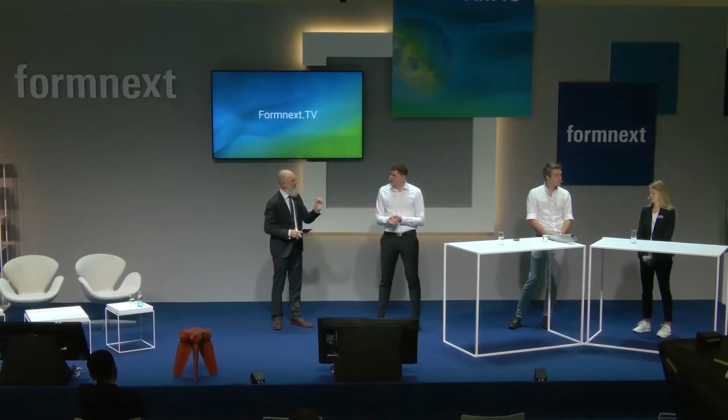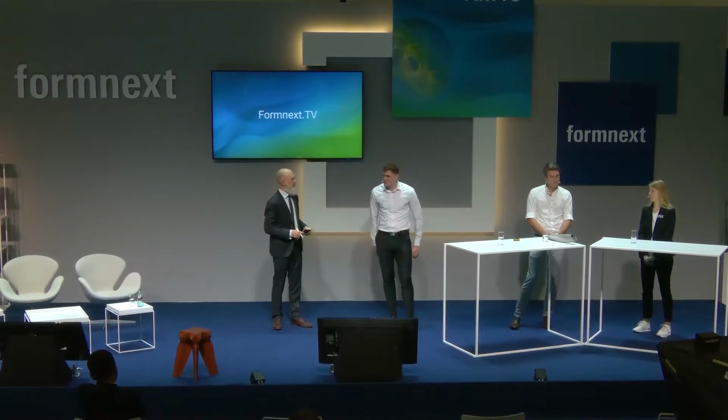But may I interrupt you? What is the droplet size? What is the finest surface you can achieve? The minimum droplet that's possible right now is 270 microns. So you can always see this shape at the surface of those parts. When you use a very small droplet, there's a surface quality of Ra 20 microns, roundabout. So it's quite smooth, but if there are some functional areas, then you machine it.